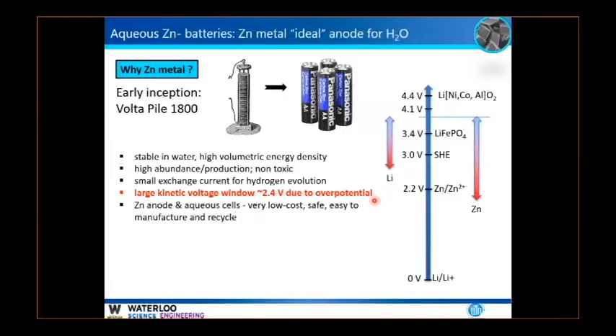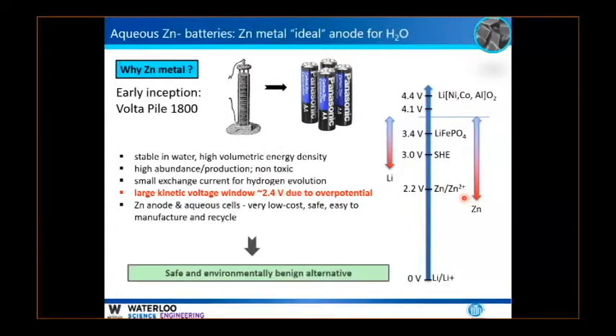And so you can use a zinc metal anode instead of complicated carbon composites at the negative side, and then you just have to choose or develop a good positive electrode, and that has to be around this voltage simply because above that you start to get oxygen evolution. So you have a good operating window, but one with limitations. But the best advantage is that aqueous systems and zinc are safe and environmentally benign.